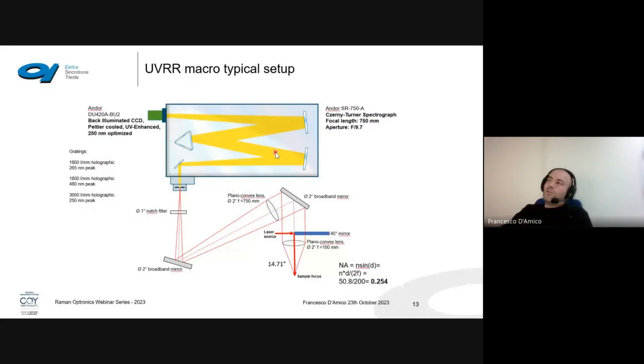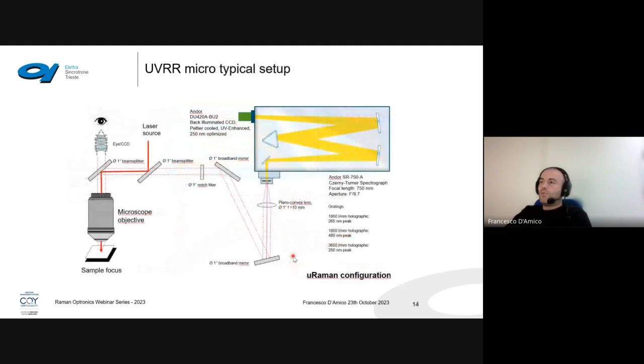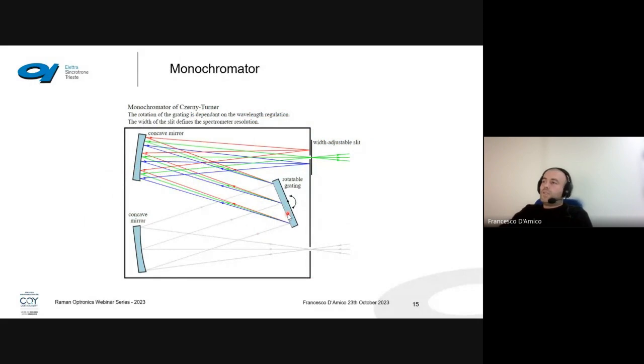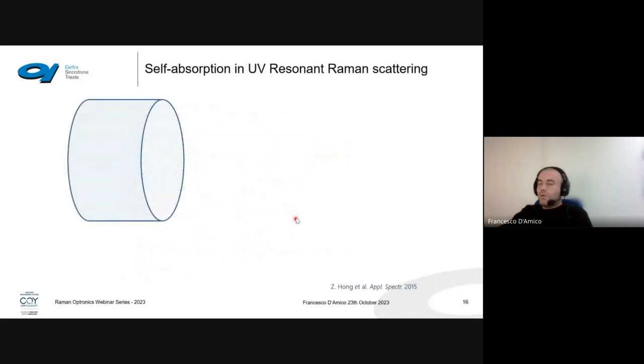What is the advantage of a measurement like this? The advantage is that, since we have a plano convex lens of long focal length, we have a big spot size, something like 100 microns. It is an advantage because, differently from what occurs in the visible range, the ultraviolet radiation could damage the sample. Therefore, tricks to avoid photodegradation are often used in UV resonant Raman, and we must take care of this effect in order to avoid photodegradation of samples.